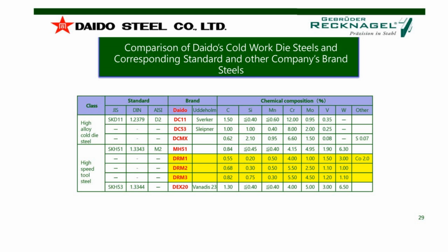Of course, Dream 1 was designed at first just for forging applications. But as I mentioned, we have some customers who need a very tough material for thick material, and therefore Dream 1 is really a perfect idea to use with a hardness of 56 to 58 HRC to solve problems in the stamping process where you have a complicated and critical shape. Therefore, Dream 1 is a perfect solution.